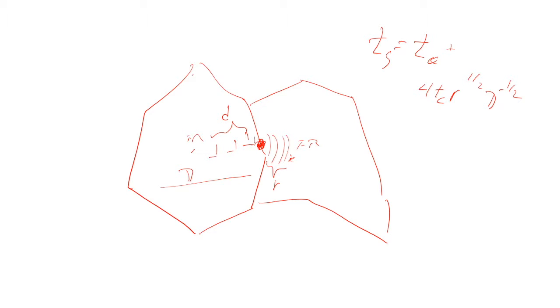I think there's only one quantitative thing that you really need to remember about this. What's the stress on this leading dislocation? If tau s is my resolved shear stress, then my pile-up stress, if I have n dislocations, is just going to be n tau s. And this comes right out of the Eshelby-Frank-Nabarro analysis. So that's the only quantitative thing to remember: the stress at the leading edge of the pile-up is going to be proportional to the number of dislocations that you have in the loop.